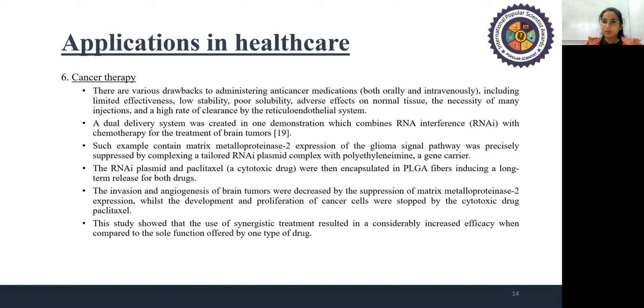Expression of the glioma signal pathway was precisely suppressed by complexing a targeted RNAi plasmid complex with a polyethylenimine gene carrier. The RNA interference plasmid and paclitaxel, which is a cytotoxic drug, were then encapsulated in PLGA fiber, inducing a long-term release for both drugs.